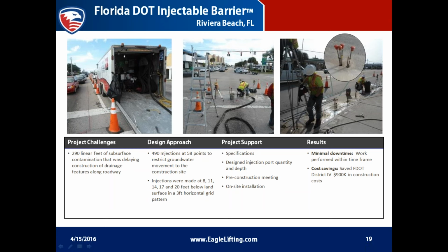In January of 2013, URETEK Holdings performed 290 lineal feet of an in-situ grout wall. They injected URETEK's 486 star geopolymer for Florida Department of Transportation. Again, it was a hydro-insensitive 2-part polymer that was injected in a highly controlled manner through 5/8" holes and 1/2" diameter steel injection rods. After hydro-lancing, or water jetting to clear utilities to 5 feet below the land surface, the injection rods were installed at 5 discrete elevations in a 3-foot horizontal and vertical grid pattern. The material was then injected through each rod, which expanded to at least 15 times its liquid volume, which formed a sort of sphere at each location. They performed 490 injections total at 58 points along 290 lineal feet of the SR5 or the US1.